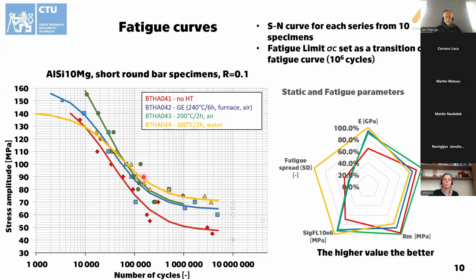Transition to the fatigue limit, I mean somewhere from 100,000 cycles to 1 million, as you can see here. This is also applicable for the T200 that shows higher fatigue strength in the low cycle fatigue transition region, although 10,000 cycles is hard to call low cycle fatigue, but the transition is higher compared to the other ones. Particularly nothing interesting to say about the non-heat treated variant, as it stands out as the worst one.